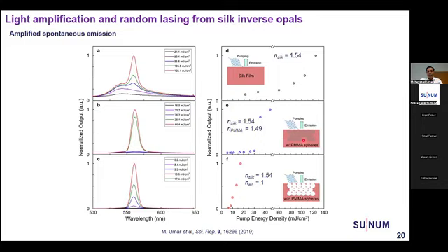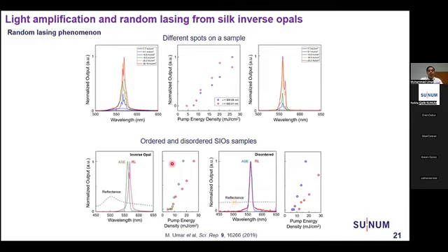And when we remove the spheres by using acetone, these spheres are replaced by air gaps. So the refractive index difference in the device is increased: air refractive index is 1 and this is 1.54. Therefore, we obtain amplified spontaneous emission with very low threshold. And then we find that, as I said, there could be some inherent cavities